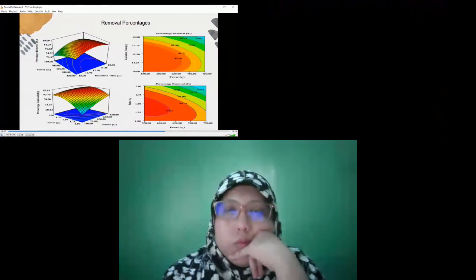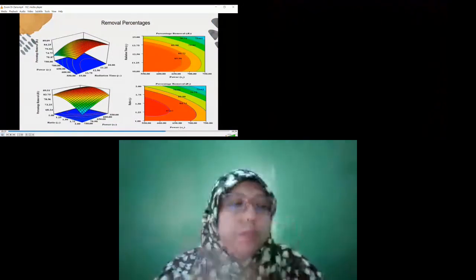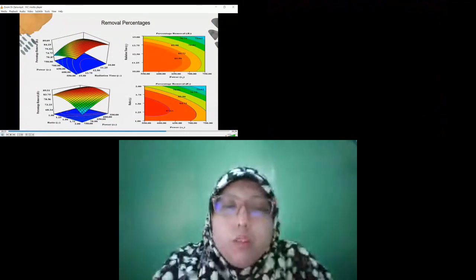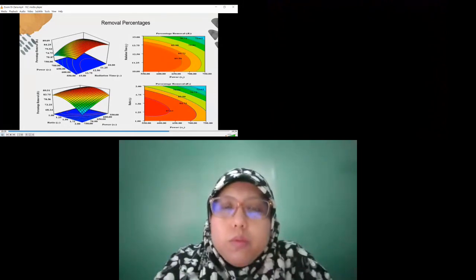We can see that as we increase the power, our removal percentage is decreasing. The same thing is happening for carbon yield and for fixed carbon. This is quite normal because when power is increasing, the active carbon network or skeleton will be destroyed and there will be more ash formation. The micropore will first be converted to mesopore and then it will burst out into macropores. And we know that macropores do not contribute to the adsorption process.